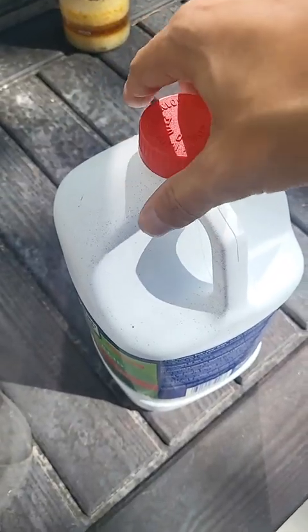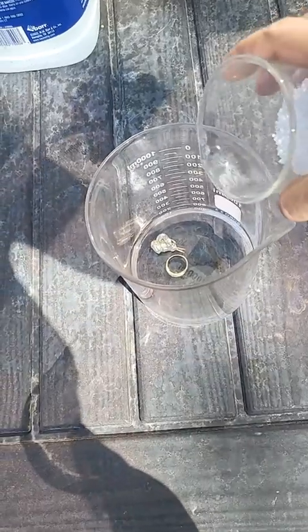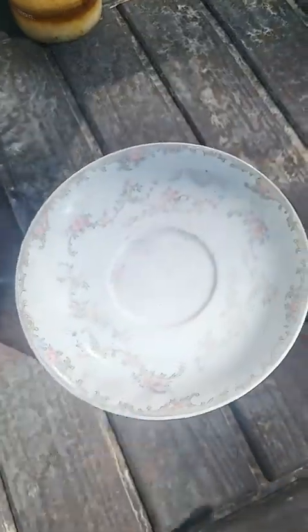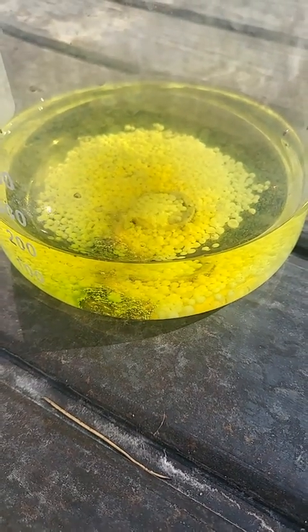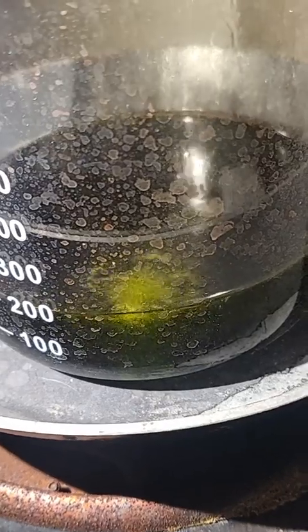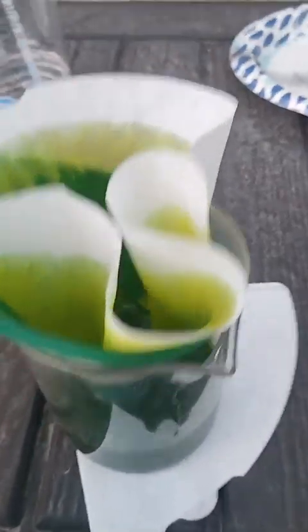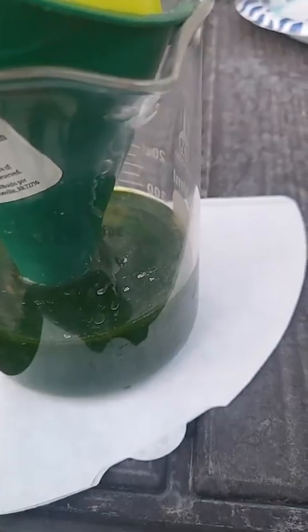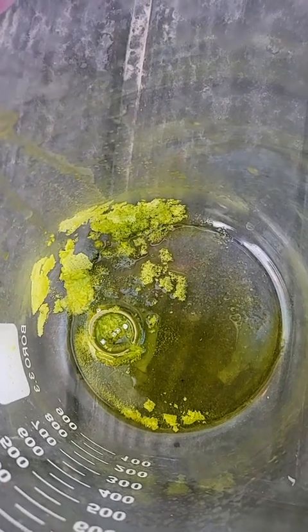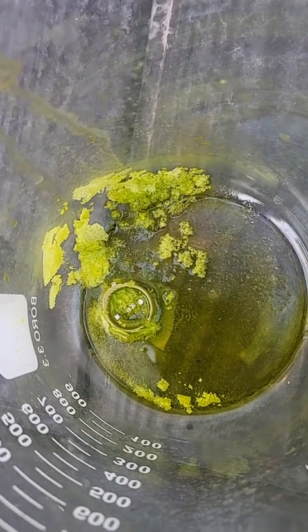I've got my clean solution — there's my gold. It didn't all dissolve. This is why you're supposed to incorporate gold instead of going straight to aqua regia. There's too much silver in the solution, so it will not dissolve this piece.